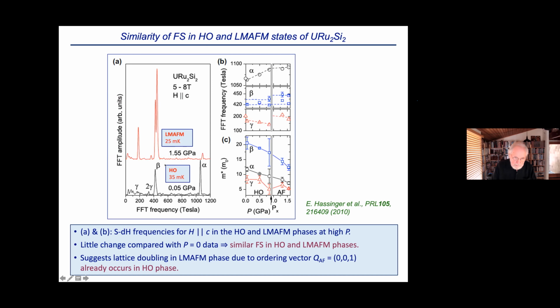This is in the hidden order phase. You see these features are very similar. And if you look at the frequencies as you go from the hidden order to the antiferromagnetic phase, you see that they don't change a lot for these different orbits as you go through this phase transition. And the effective mass actually goes through rather smoothly. So again, this suggests similar Fermi surfaces in the HO and large moment antiferromagnetic phases,